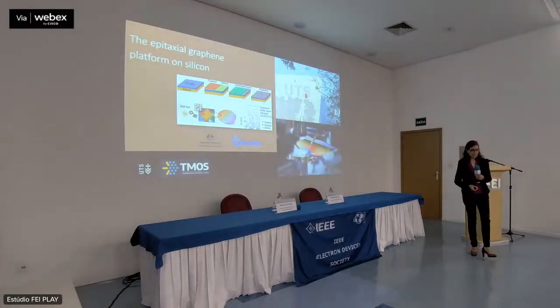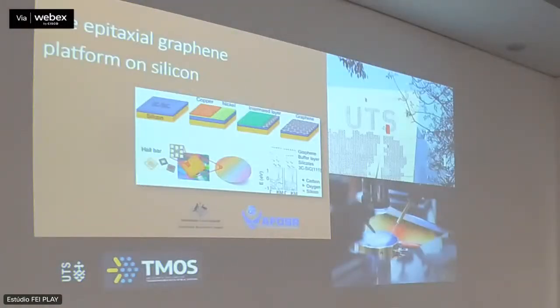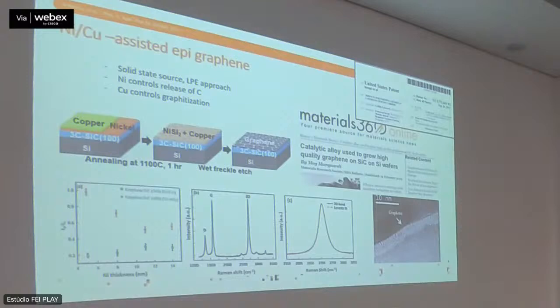And that's where we started working, as I said, about 10 years ago now, and we came with a different approach. Instead of just using sublimation, thermal decomposition at high temperature, we had to come up with a way to relax those constraints on the defectivity of the layer. And what we decided to do was to use catalysts. Catalysts usually always help. They help to reduce the temperature. They help to make processes fast. And particularly, what we came up with was to use an alloy of two different catalysts. In this case, we chose copper and nickel.